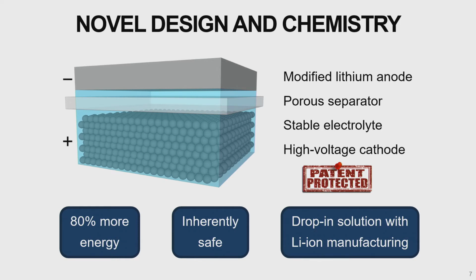So what we are doing is really changing the chemistry of the lithium-ion battery system with new materials throughout most of the battery. It starts with the liquid electrolyte inside the battery. Currently, lithium-ion uses a mix of organic solvents that's highly flammable, and that actually leads to many of the challenges associated with lithium-ion batteries, both in terms of safety, of course, but also in terms of the chemical stability of the system. It prevents us from using better electrode materials that store more energy in lithium ion because the electrolyte itself is not stable enough to operate safely and stably with those kinds of energy-dense materials.